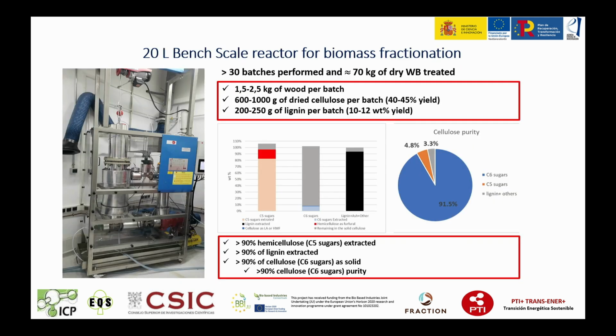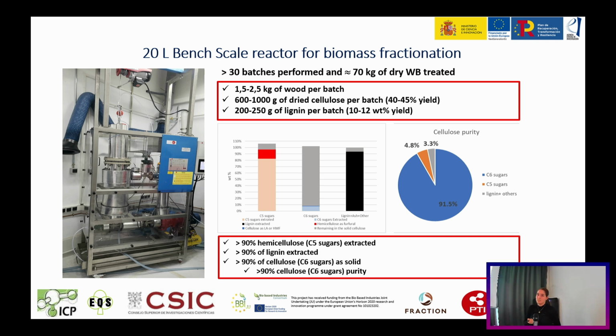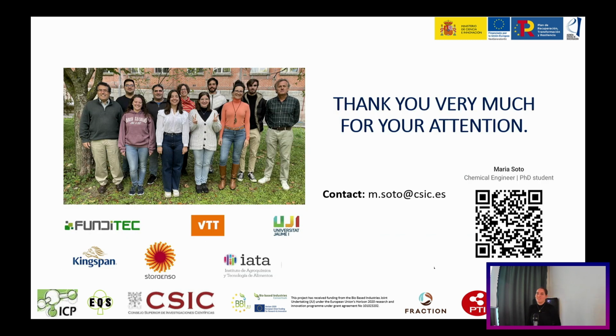sugars. So finally, we have scaled up this process to a 20 liter bench reactor, where we have performed more than 30 batches and treated around 70 kilograms of wood. And we obtained the same results we got at laboratory scale, so this process is reproducible. And today we have the capacity to treat between 1 to 3 kilograms of wood and obtain 600 grams of cellulose per batch and 200 grams of lignin. So that's all. Thank you for your attention.